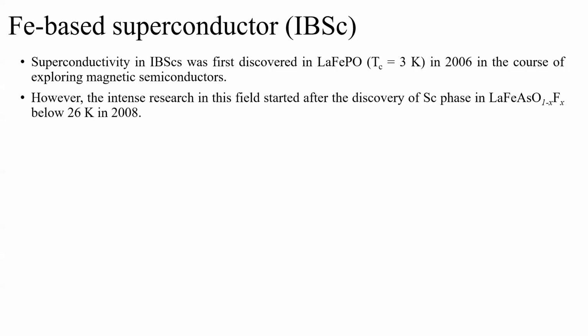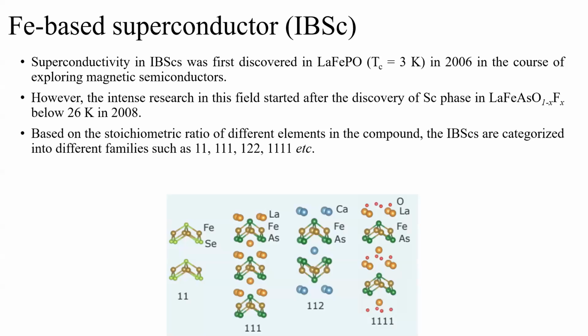But later, when they did the electronic structure study, they found that the near Fermi states, which is also known as the valence band, the density of states in the valence band was mostly constituted by the iron. So then they started calling these compounds iron-based superconductors. Now, after intense research on these compounds, people found that there are actually many types of iron-based superconductors. Although they have different numbers of elements, they have similar structures and similar properties. So then they categorized these compounds into different families.